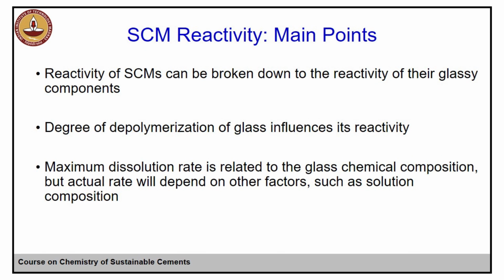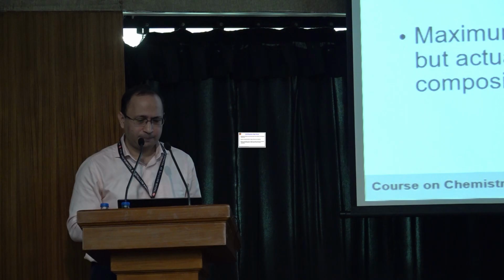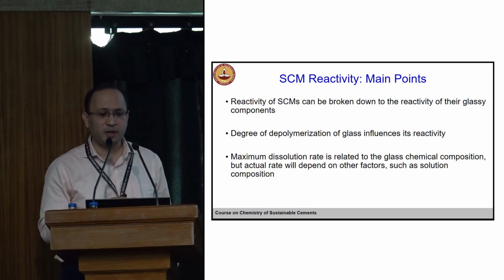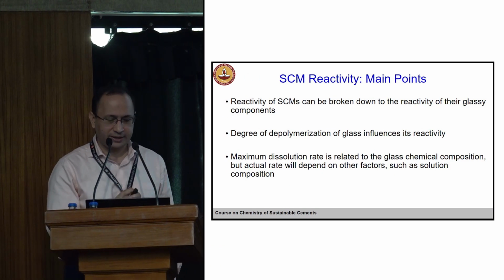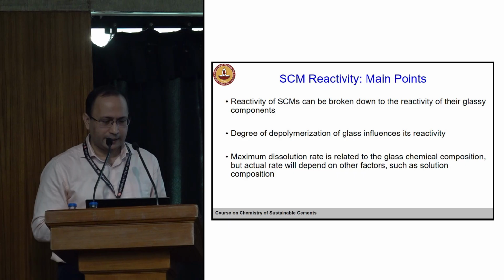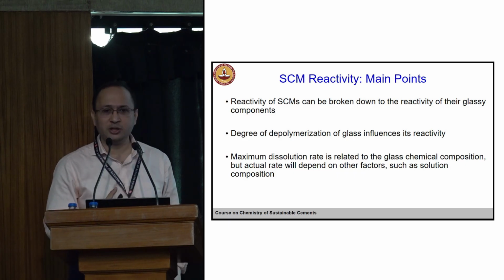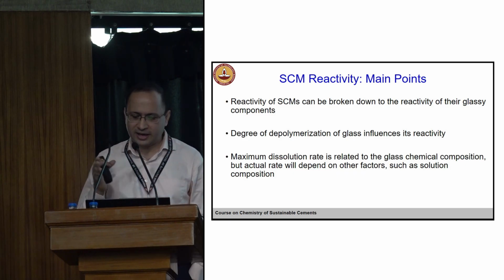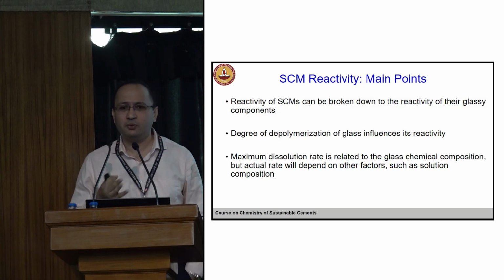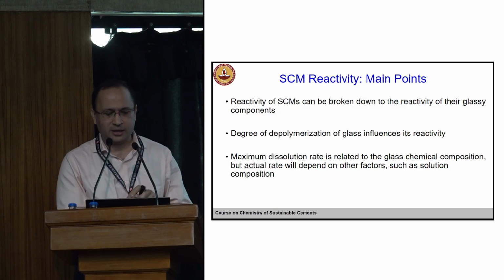So basically we can break it down to the reactivity of the glassy phase, right? We can look at the extent of depolymerization because that will affect the reactivity. And the maximum dissolution rate is related to the chemical composition, but actually the rate will depend on your conditions like solution condition, pH, temperature, things like that.